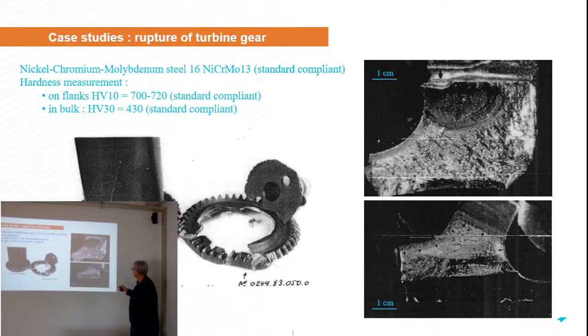You can see here a very typical fracture surface where you can see the two zones I detailed before. The zone where you have the propagation of the crack, and here the final fracture occurring on the very last cycle. And here you can see the beach mark I detailed before.